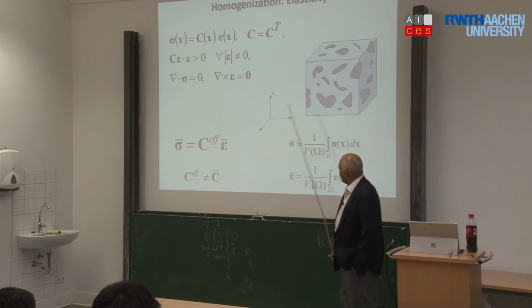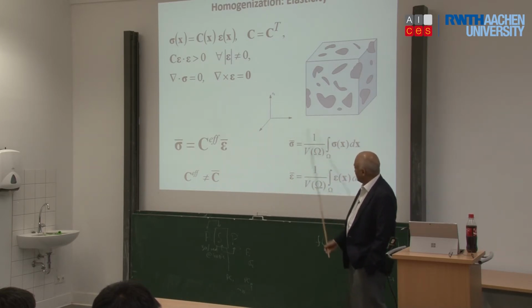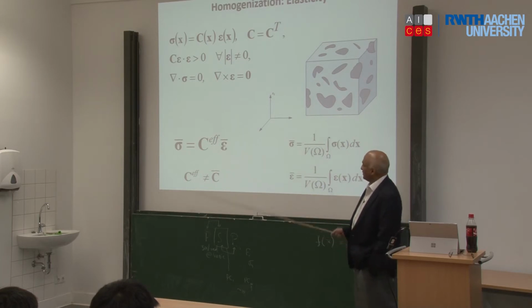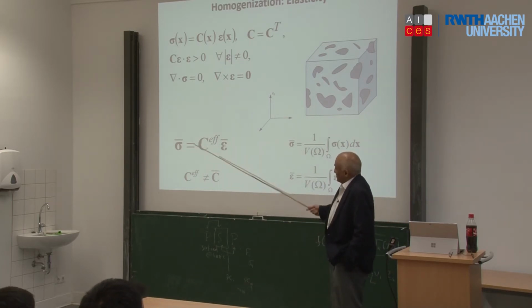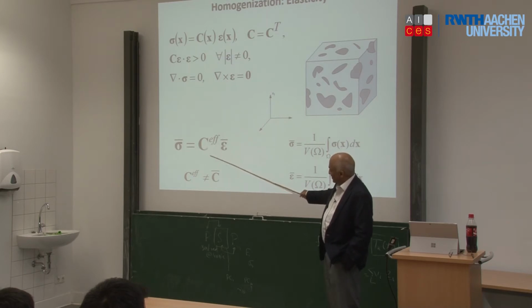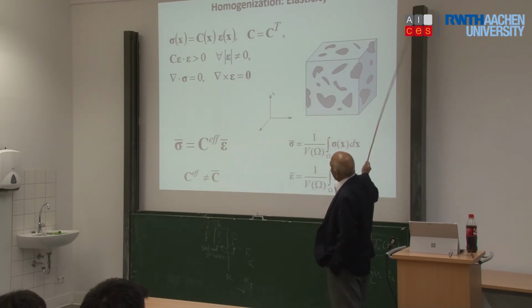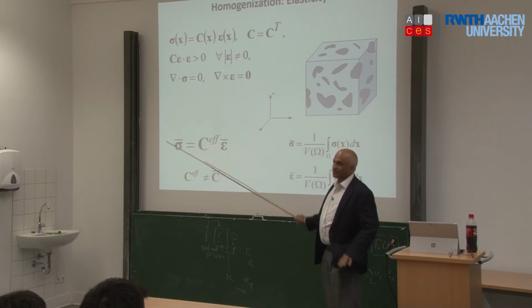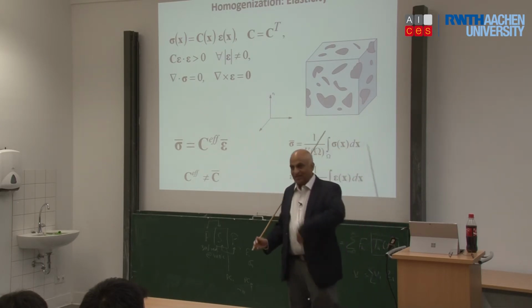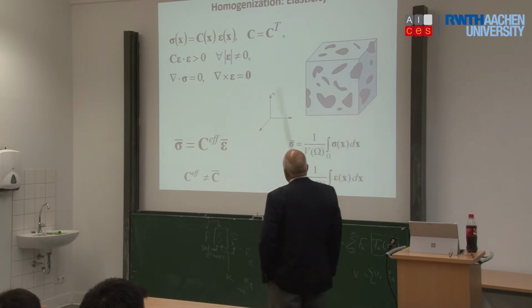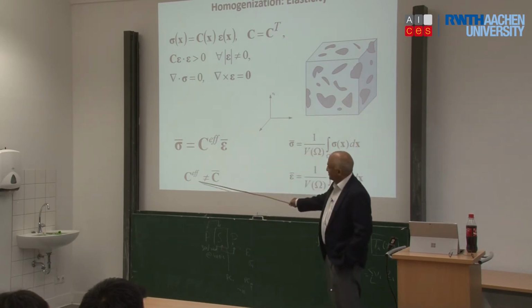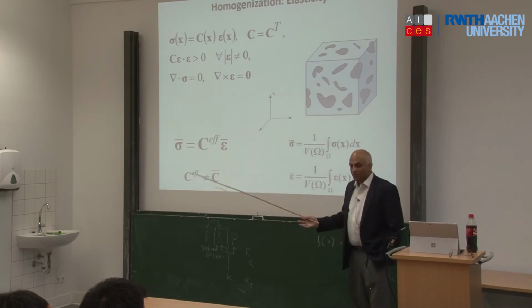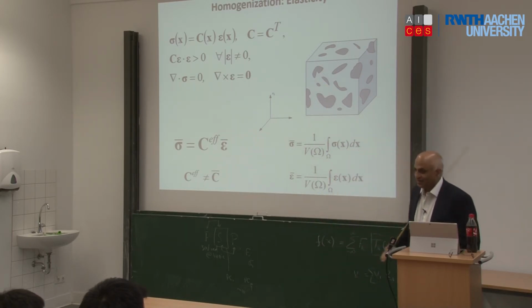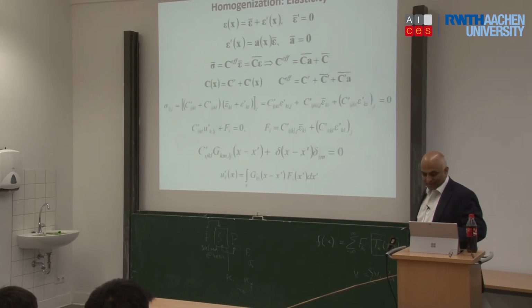Here sigma bar is simply the volume average and epsilon bar is simply the volume average. That's the definition. And effective stiffness is the homogenized property, because if this exists, basically what you're saying is when I go to the higher length scale, I can assign this and I should have basically the same response at the higher length scale. Okay? The problem is the effective value is simply not a volume average of this. If it was, life would have been simple. You didn't have to worry about anything, and nobody would do any mechanics anymore, right? So it turns out it's not just a volume average. Now,